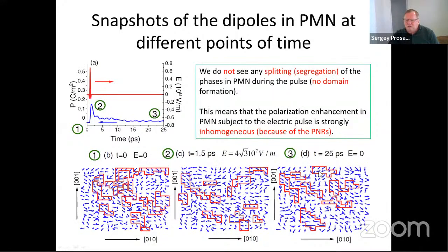I also want to say that the microstructure, during the pulse, before the pulse, and after the pulse, is different. So the polar nanoregions change during this pulse and after this pulse. So we have a strongly inhomogeneous response of the matter to these electric pulses in PMN, in relaxors.